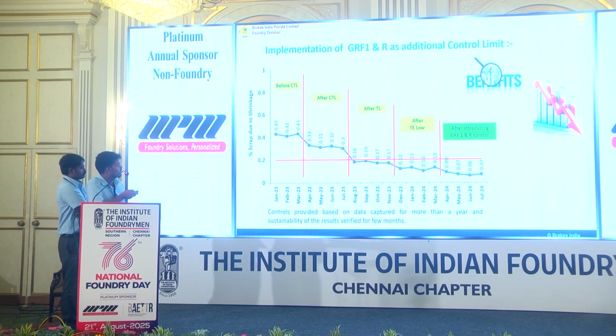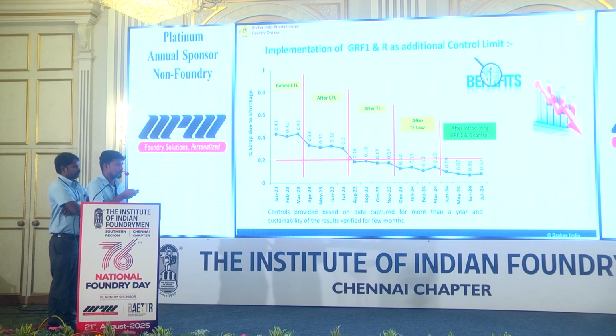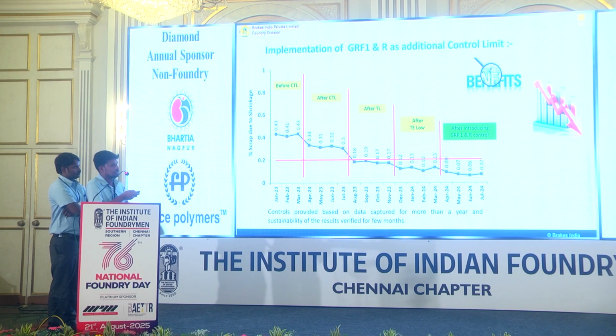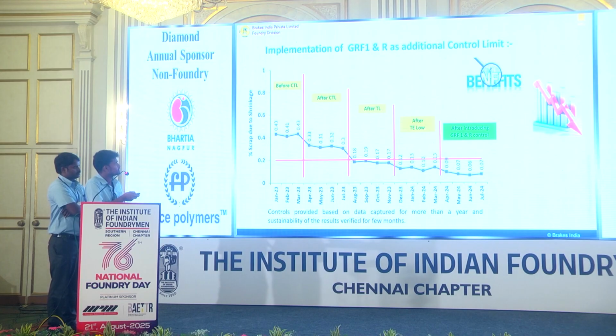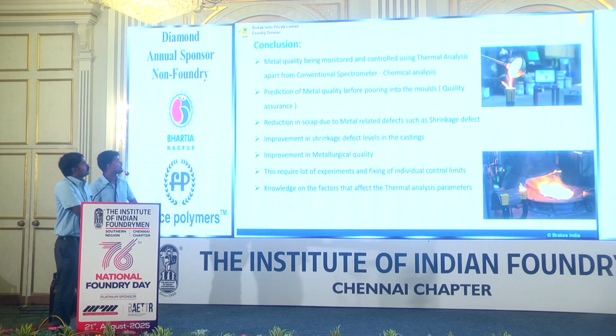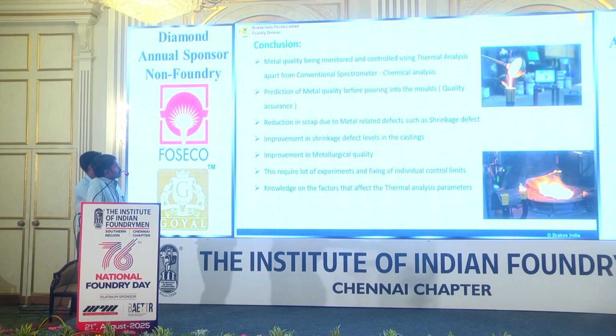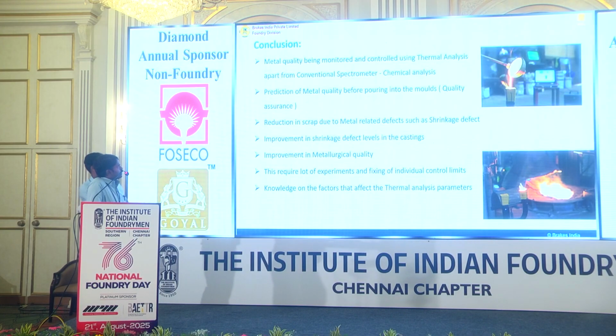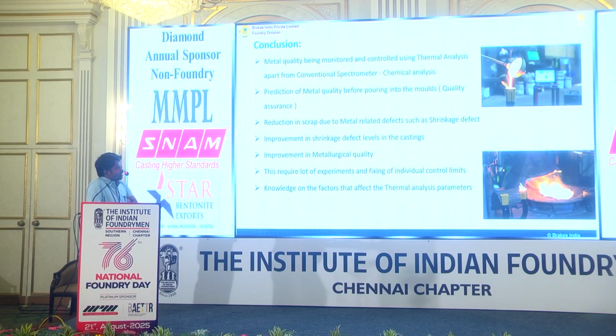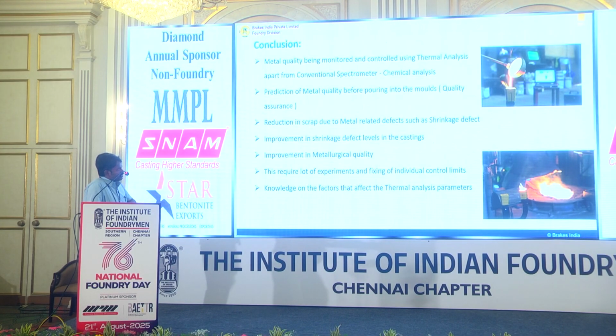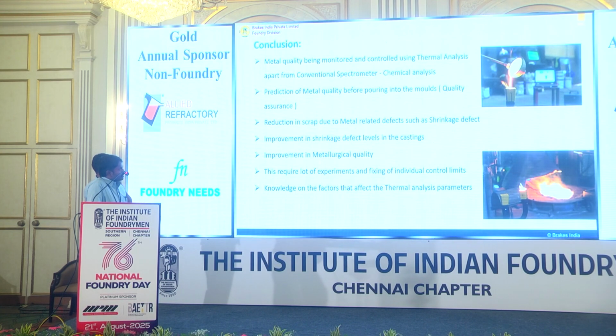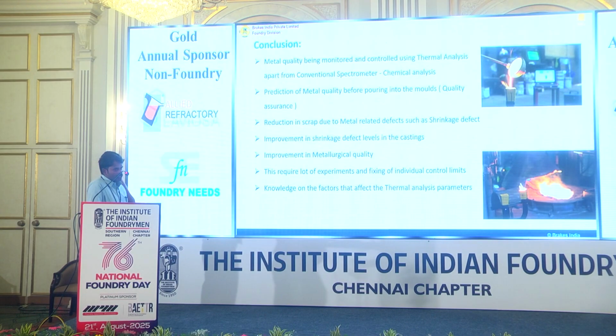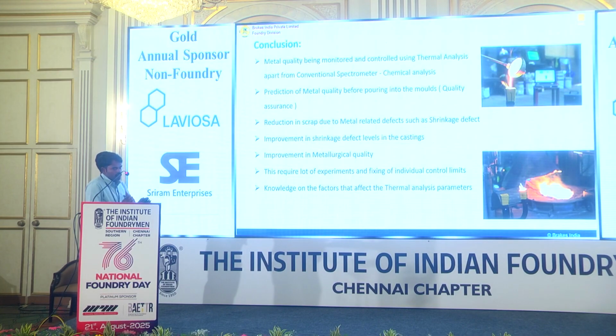After putting in this thermal process parameter control, for some of the parts we eliminated the sinkages. So, through melt quality being monitored and controlled using thermal analysis, apart from the conventional spectrometer, prediction of metal quality before pouring is more of a quality assurance technique than quality control. It brings reduction in scrap due to metal defects such as shrinkage, improvement in shrinkage defects in the castings, and improvement in metallurgical quality. This requires a lot of experiments, and a lot of data collection is needed before implementing this thermal analysis system.